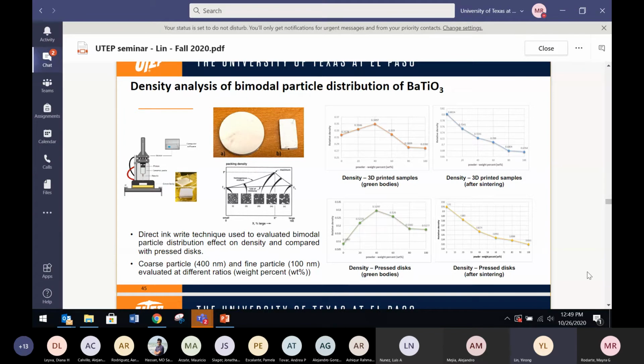If you want to have a good green body density, then probably you have to mix these particles together. But if you want to have a good final density after sintering, you want to use more small particles because small particles always sinter better than big particles, right? This is what we learned, and this is what we find. We're in the middle of getting this thing published. Next slide.